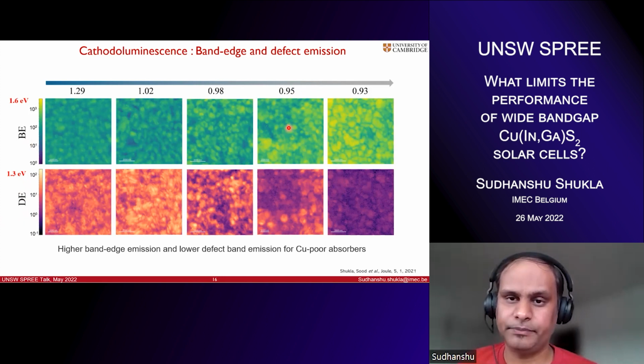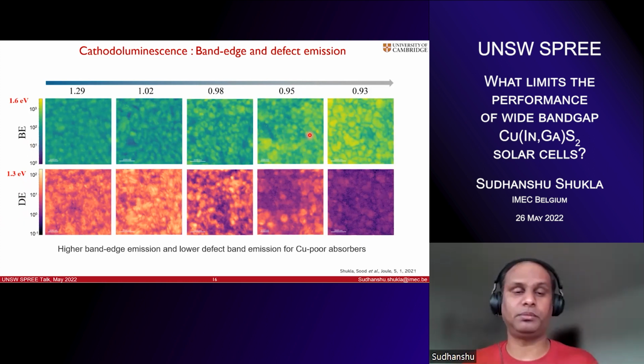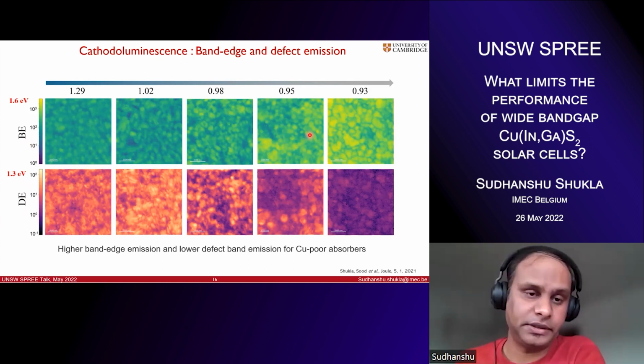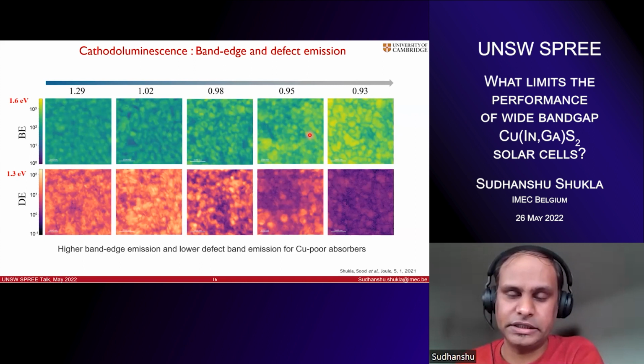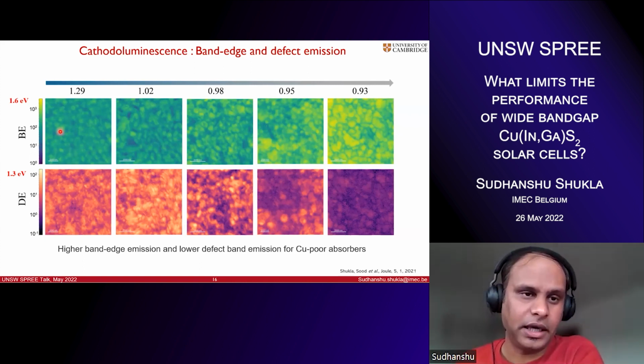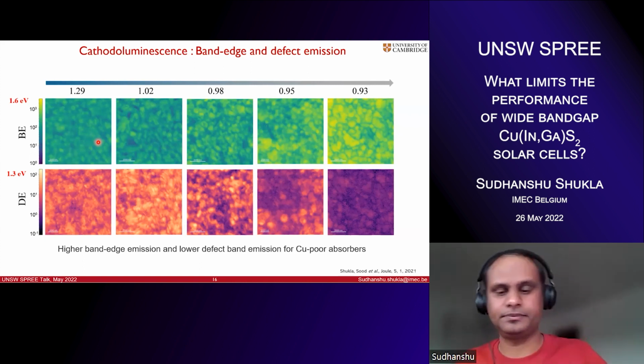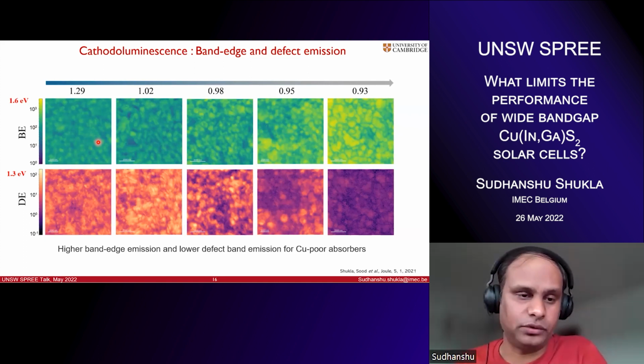And you also see kind of grainy features here. So you have kind of grain boundaries appearing. It looks like a grain boundary where you have a low emission. So you might have lossy grain boundaries, but we are still investigating these films in more detail and trying to see what these could be. And that study will be out very soon.